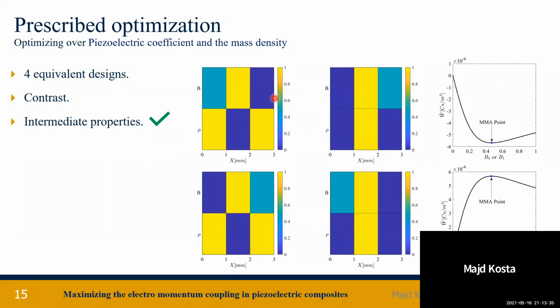If you consider only one step, for example, these two designs in here, one step gives us the same absolute value, but with a negative sign. And of course, we can see again that we got intermediate values of piezoelectric coefficient, which has been examined and proved that it is true.